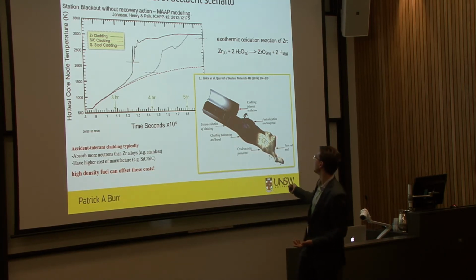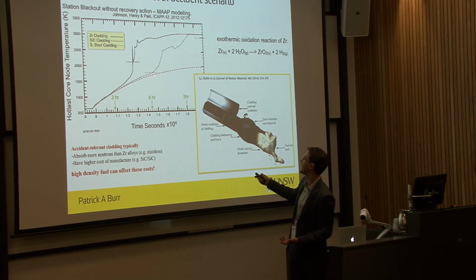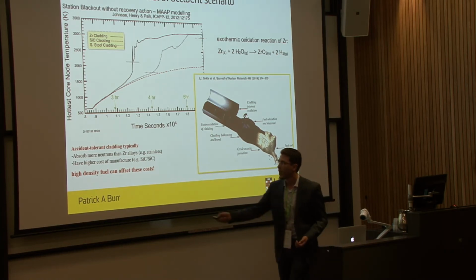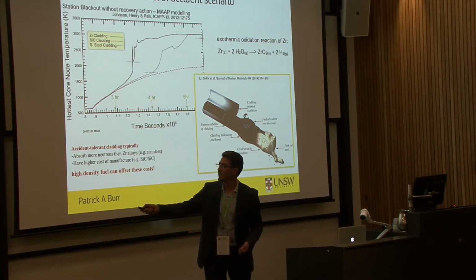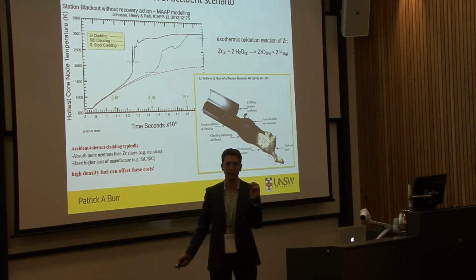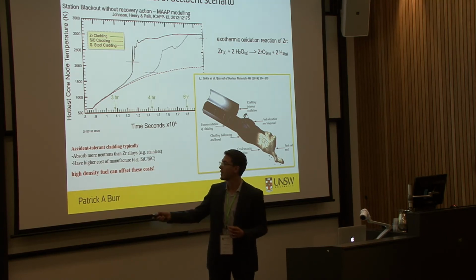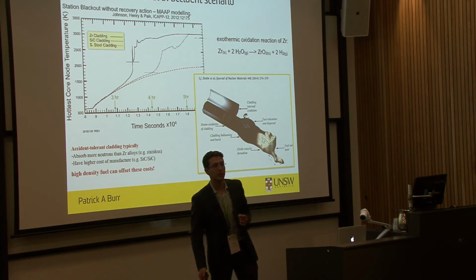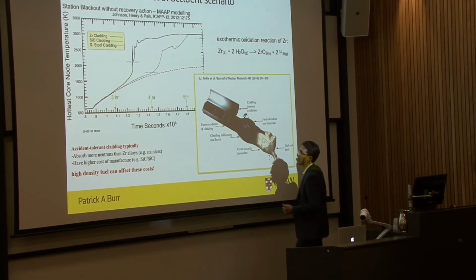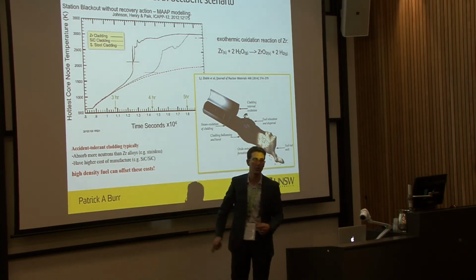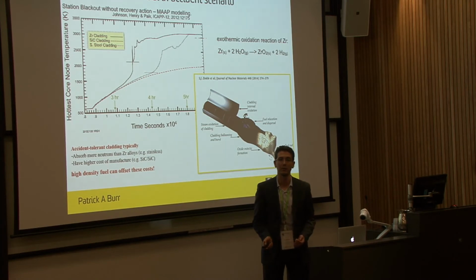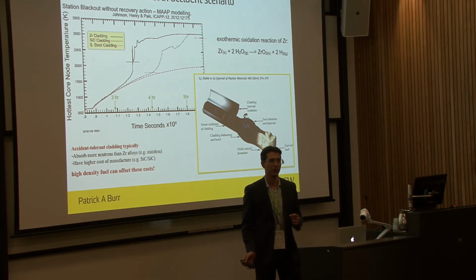This picture here, which I lifted from the review from Zinkle, just shows basically the same things in a pictorial representation. And you can see that as the temperature increases, the cladding oxidizes. As it oxidizes, it gets thinner. The amount of metal available gets thinner and gets softer because it's hotter. So it can balloon and burst due to the pressure from the pellet, and then it can melt. The point of accident-tolerant fuels is to try and push this part and this part as far later as possible, so like to the right of this graph, and try and buy time in an accident scenario. But importantly, we must do this without compromising on the economics of power generation.